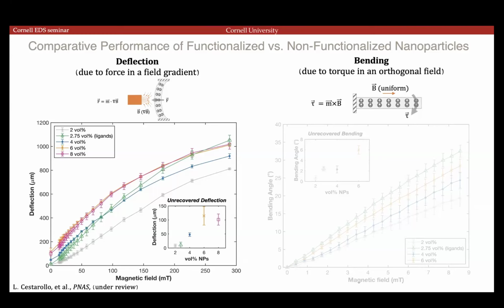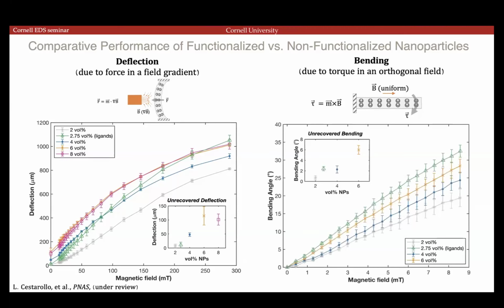And coming back to the anisotropy question. When we align the particles, I said that these should also be very responsive to an orthogonal field and should torque. So we can also do bending experiments. In this case, we apply a field orthogonal to the direction of those magnetic moments. And here, again, the ones that are better aligned, so those particles that have the ligands on them, get a higher bending angle regardless of the volume concentration, or regardless of the field applied.